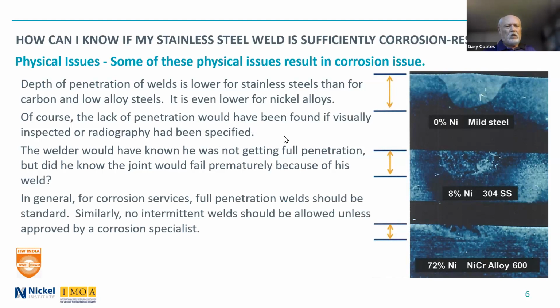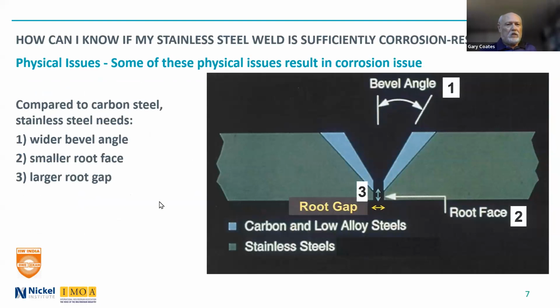In a similar manner, we don't want intermittent welds, because with intermittent welds you can also get crevices created, and in many environments, crevice corrosion. Now, there are cases where intermittent welds are allowed, but you want to have it approved by the corrosion specialist who knows exactly what is in the solution and whether crevice corrosion is likely or not. And typically, and I've shown these slides before, compared to carbon steel, stainless steel needs a wider bevel angle, especially with thicker plate, a smaller root face, and a larger root gap.